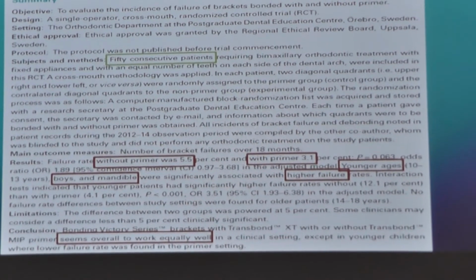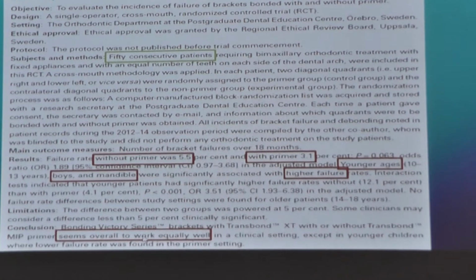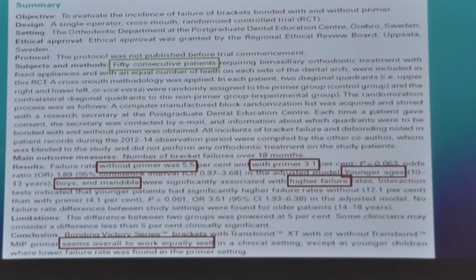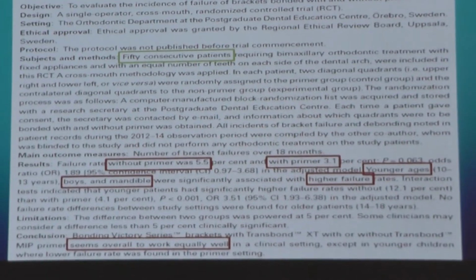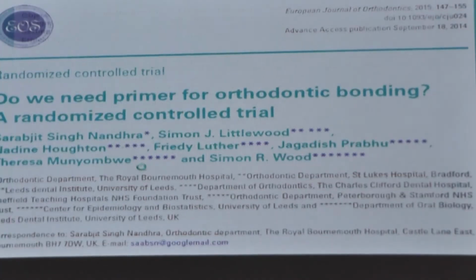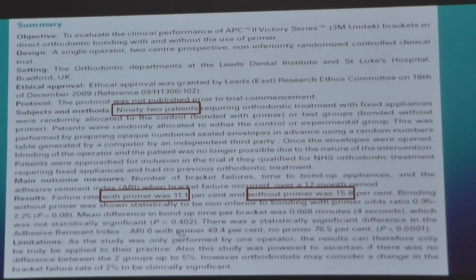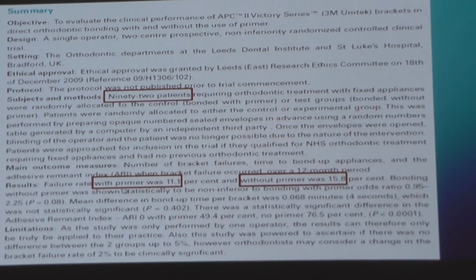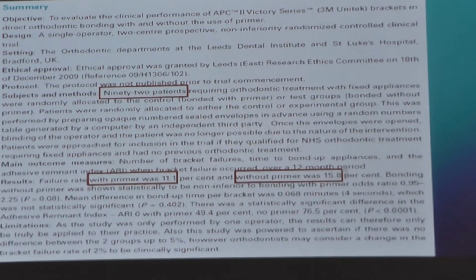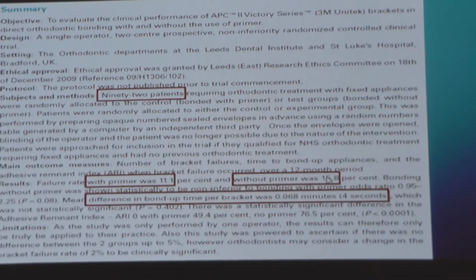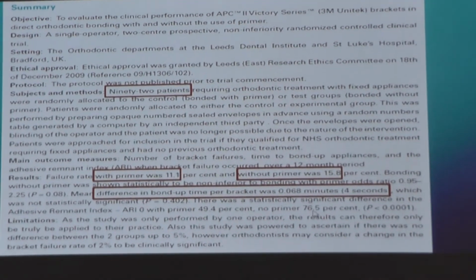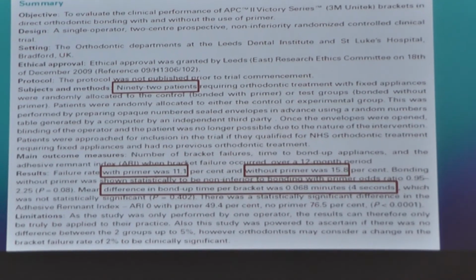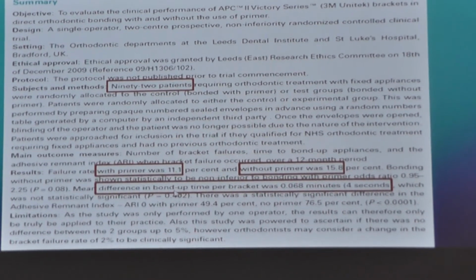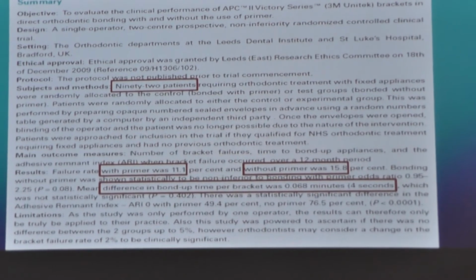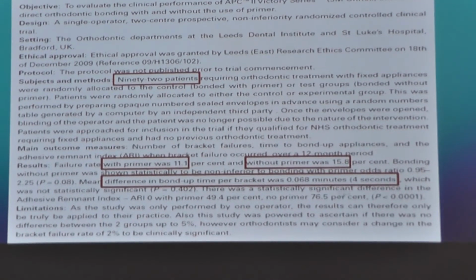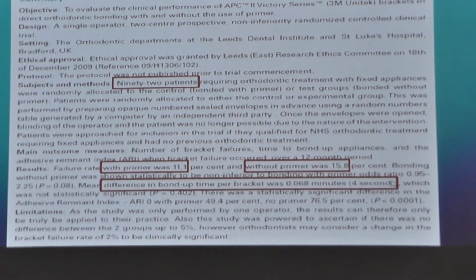Okay, so they say that it seems to work overall equally well because they did not find a statistically significant difference, but clinically it could actually mean a significantly higher failure rate if we do not use the primer. And also a similar study had much higher failure rates, which was interesting, 11%, and again without primer it was 15%, and again they said it could be clinically significant, although it is not statistically significant. And one reason why we would like to avoid primer perhaps is also saving chair time. But they found that they only saved 4 seconds per bracket, so it's not very significant.